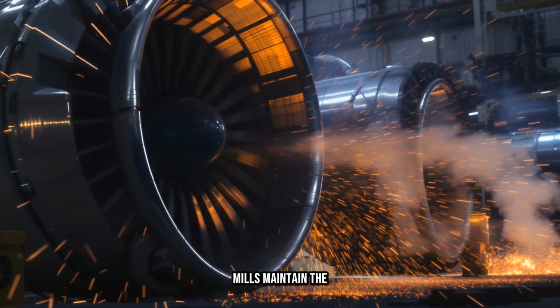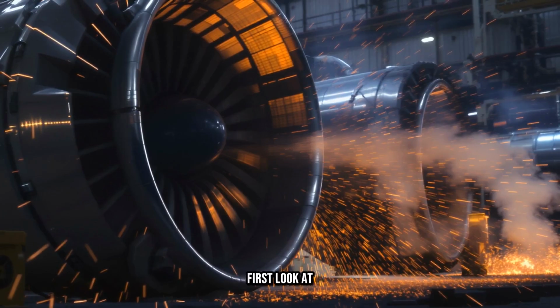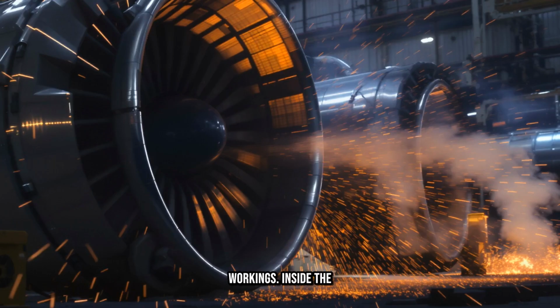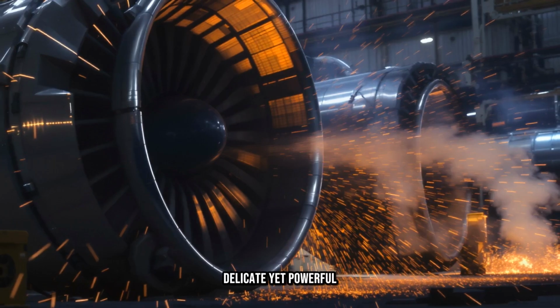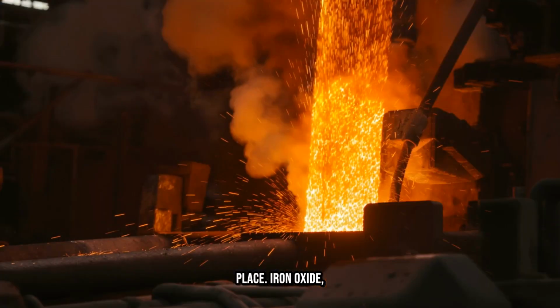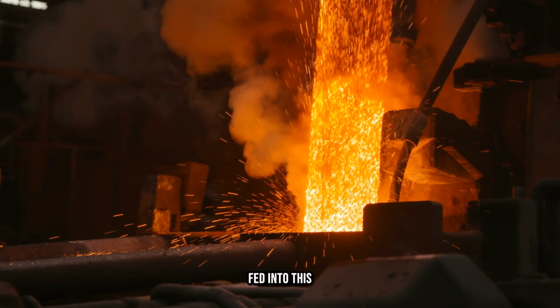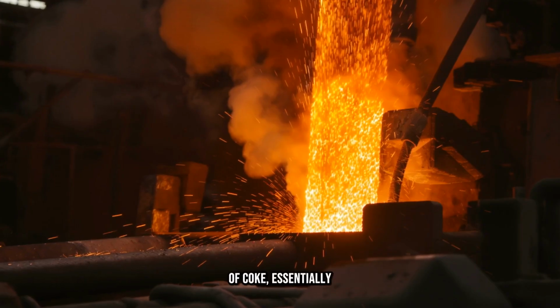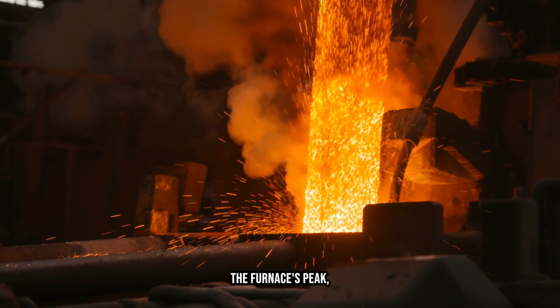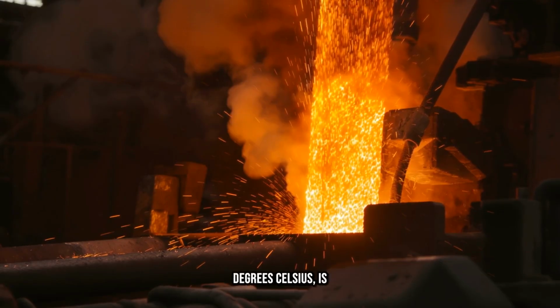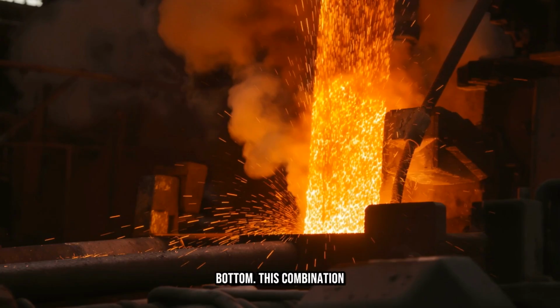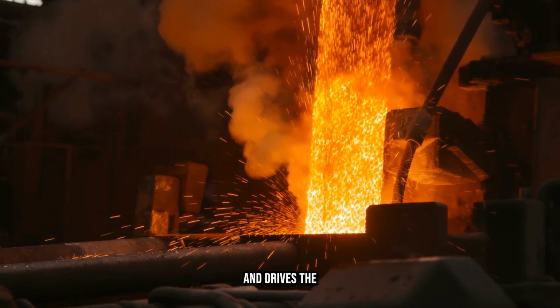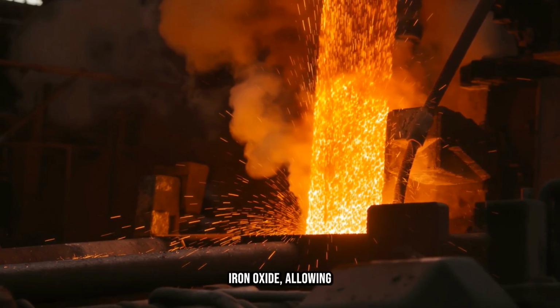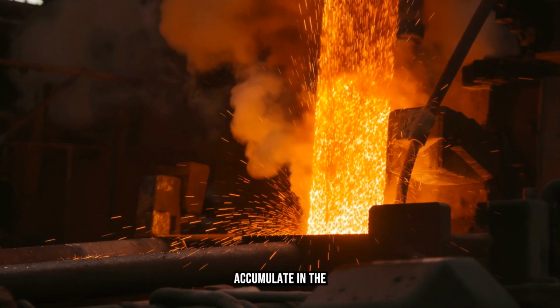To grasp why steel mills maintain the heat of their furnaces, we must first look at the furnace's internal workings. Inside the blast furnace, a delicate yet powerful chemical reaction takes place. Iron oxide, in the form of ore, is fed into this towering structure along with a mixture of coke, essentially carbon, and a flux material such as limestone. At the furnace's peak, raw materials descend while a superheated blast of air, reaching approximately 1000 degrees Celsius, is introduced from the bottom. This combination generates extreme heat and drives the chemical reactions necessary to reduce the iron oxide, allowing molten iron to accumulate in the hearth.